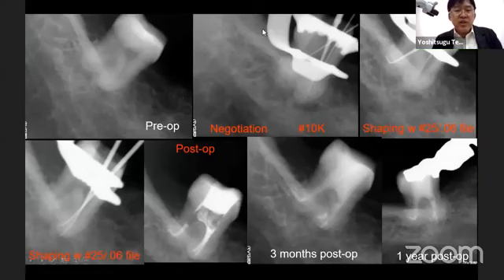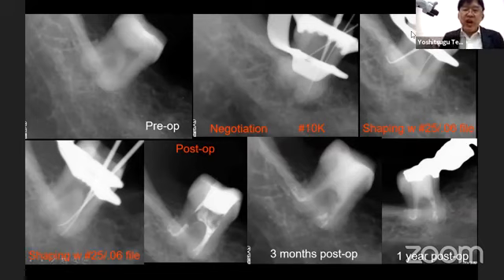So let me show you 3 cases from my practice. You see the crazy curvature. I negotiated the canals with a number 10 K file and created a glide path with 10 and 15 K files. Then I used the reciprocating motion with the 25/06 instrument. Then I did the same for the mesiolingual canal and the mesiobuccal canal. And this is a post-op, and 3 months and 1 year, showing nice periapical healing.